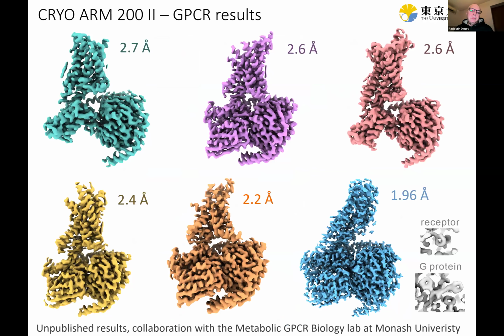So I also collected quite a few GPCR datasets, G protein coupled receptor datasets. This is a real world sample from our collaboration with the metabolic GPCR biology lab at Monash University. So here you see the reconstructions. Overall, they correspond pretty closely to what we have been getting from the Cryos G4, the Schottky FEG Cryos, which I showed in the apoferritin comparison plot. And similar to what we got from the Cryos G4, one of the GPCRs also reached sub-2 angstrom resolution. I haven't checked the PDB recently, but a few months ago it was still only the third G protein coupled receptor structure below 2 angstrom, the other two being done on the 300 kV Cryos G4. So overall, the impression is that the results from the Cryo-200 are very similar in performance to the results from the Cryos G4, a 300 kV machine.